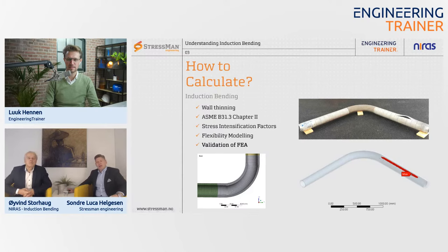And then we got the material properties from someone who was testing the base material, also the bent material, and we could model that into our calculation. And it burst over here, as you can see. In our analysis, it also indicated that it was going to burst there. This is the plastic strain in the pipe. And we got approximately the same range of pressure as well, where it was supposed to burst. And this confirmed our numerical model.